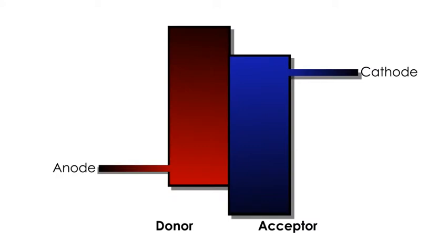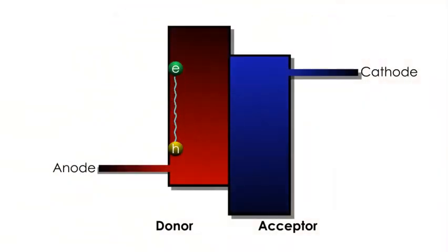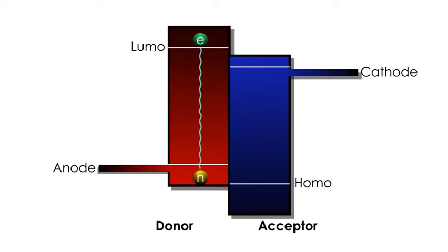Here we see the basic mechanism of photocurrent generation where light absorption leads to a bound electron-hole pair or exciton which can diffuse to the donor-acceptor interface where it undergoes a charge transfer reaction forming a hole in the donor layer and an electron in the acceptor layer, followed then by charge conduction.